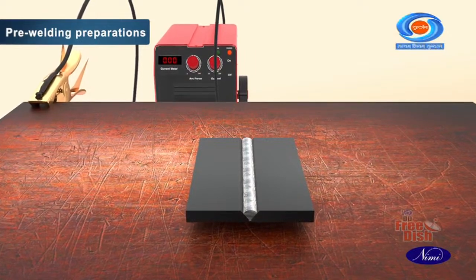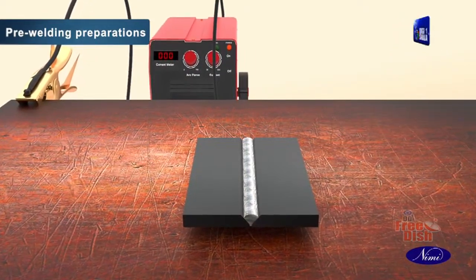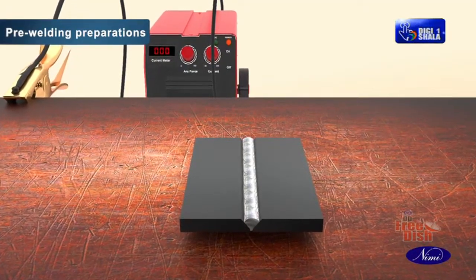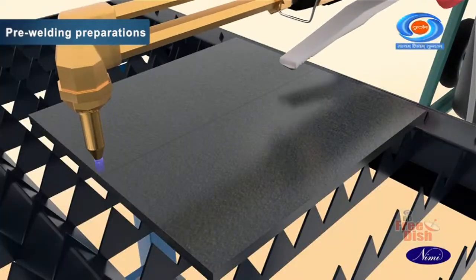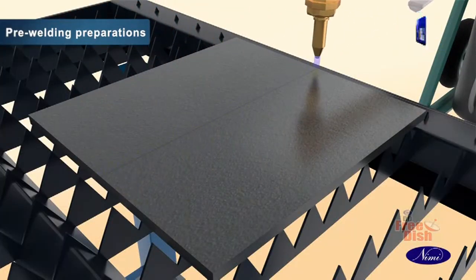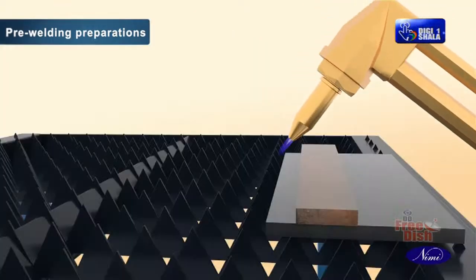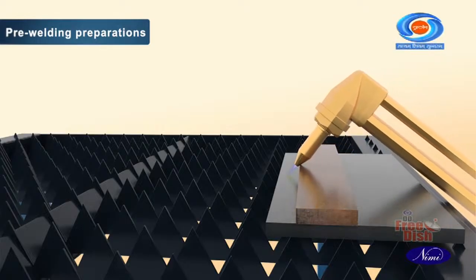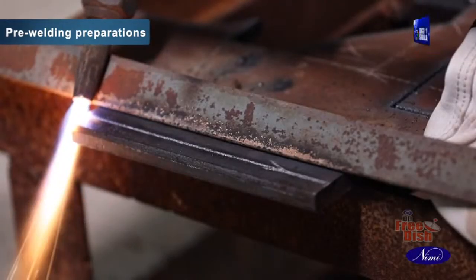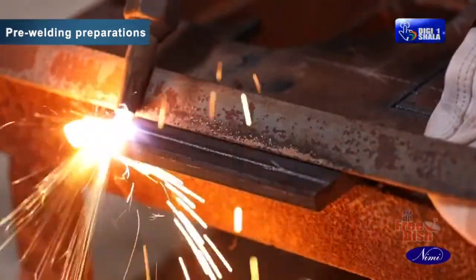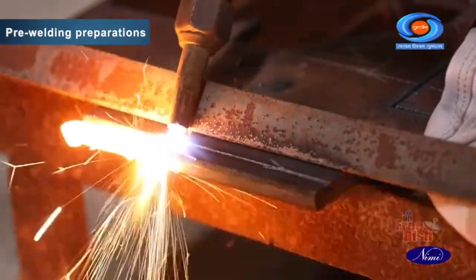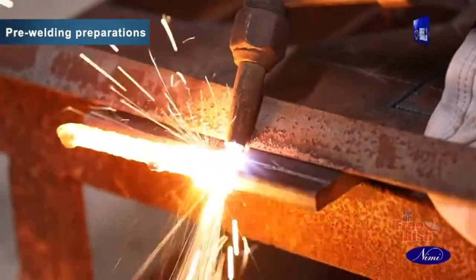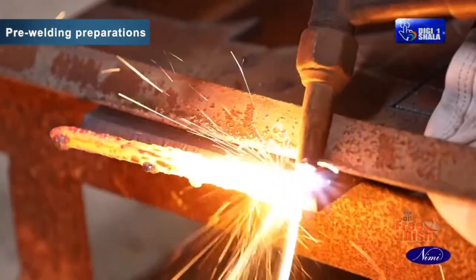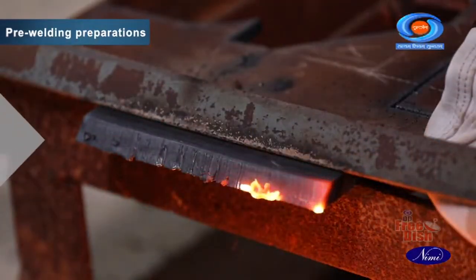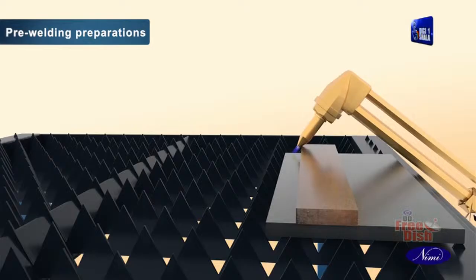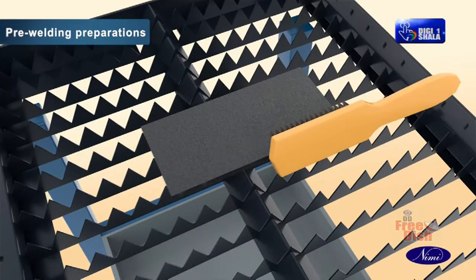Let us see the procedure for the single V butt joint on MS plate 10 mm thickness in flat position by SMAW process. Straight cut 2 10 mm thick plates by gas cutting as per drawing and grind them to size. Bevel the edges of each plate to 30° angle by gas cutting. And file the root face as per drawing and cutting the bevel.